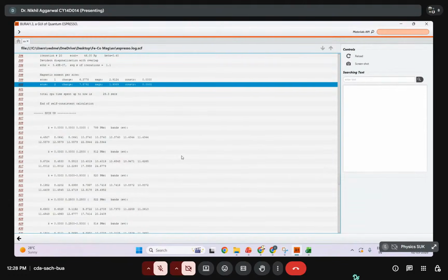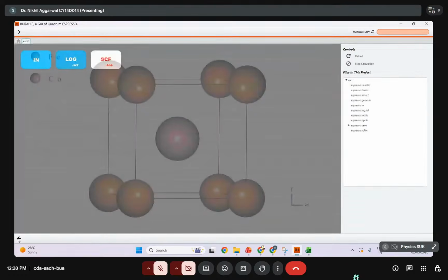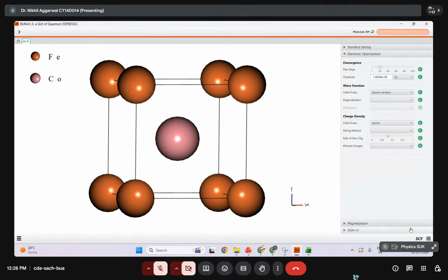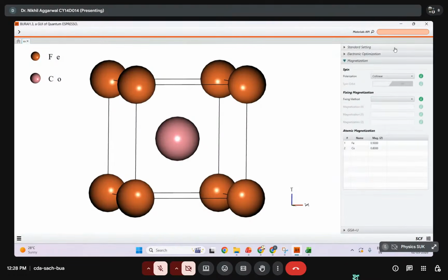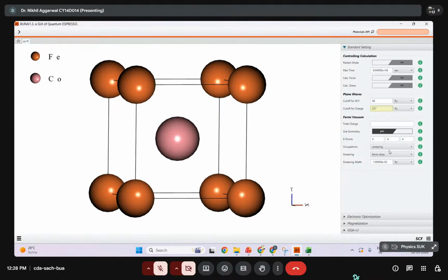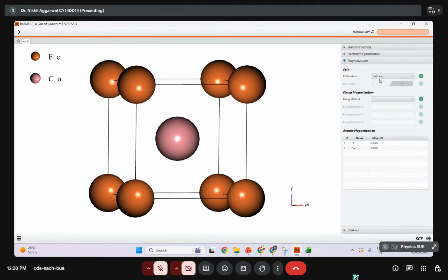I am sure how to put the magnetic moment calculation must be clear to all of you. I'll just quickly summarize. Under standard settings, you have to keep the cutoff values. So the SCF convergence calculation to obtain the cutoff value is a must for the magnetization. Then go to the magnetization, and under the magnetization keep the polarization as collinear by default. Obtain the cutoff value for each one of them, keep those values, and then obtain the total magnetic moment and the individual magnetic moments. I'm sure this must be clear.